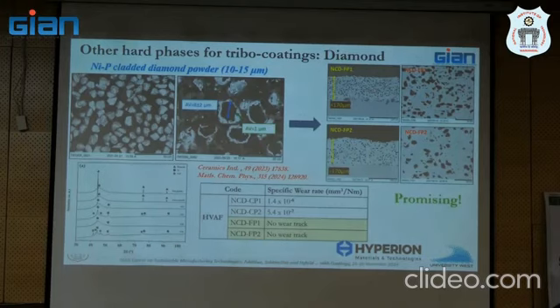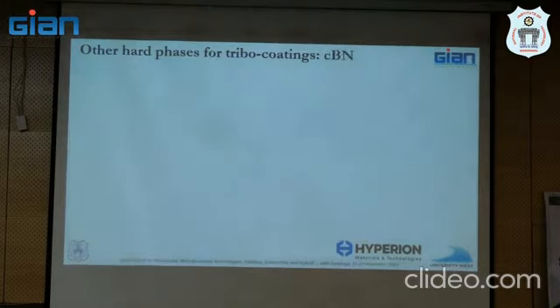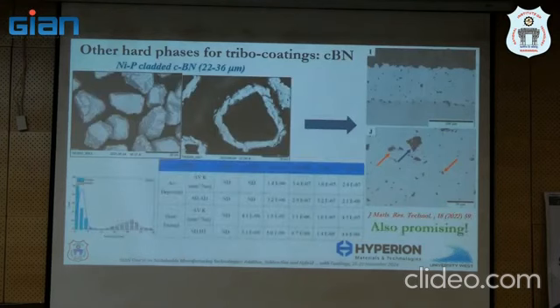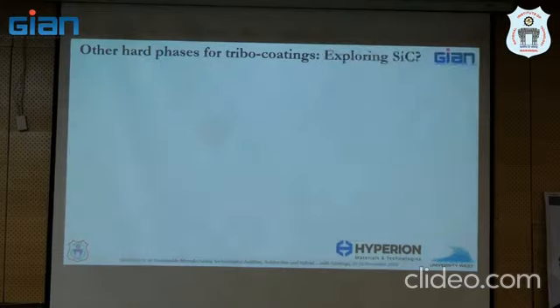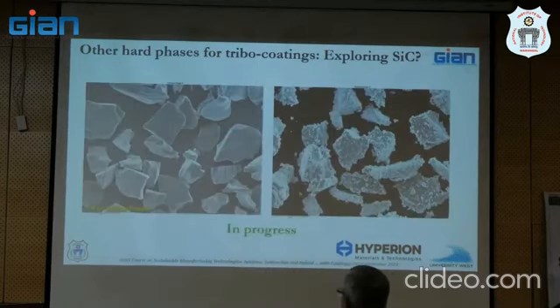Because of that, we also got encouraged to look at cubic boron nitride. We have done much the same, and again, pretty nice properties, 10 to the minus 8, 10 to the minus 7 specific wear rate. This is also something we have published. But the next step for us is silicon carbide, because this is cheap. I don't mind losing 80% silicon carbide when I'm spraying. I don't want to lose 80% diamond or CBN, but silicon carbide I don't mind losing. So this is something we have started doing.